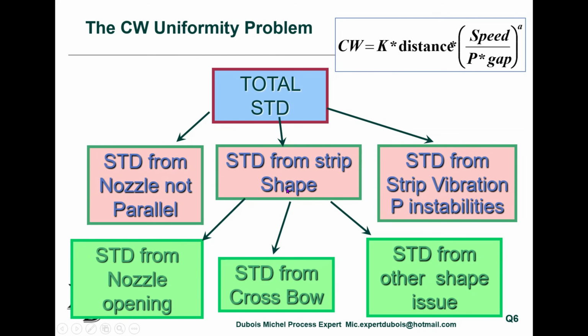Also, it could depend on the strip shape. And what do we have in strip shape? We have crossbow, because in that case, the nozzle to strip distance varies. It could also be related to the nozzle opening. Sometimes the nozzle could vary along its length. And we have other issues that are minor. And finally, we have the instability in the wiping pressure, or the strip vibration, because strip vibration is related immediately to nozzle to strip distance.